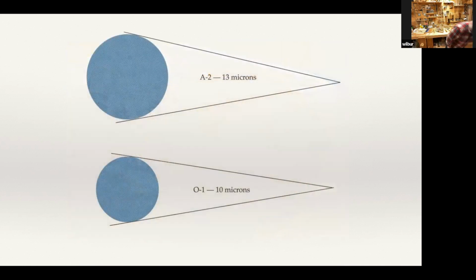Well, as it turns out, these carbides will settle out on a particular size, and this is a combination of how you treat the steel as you make it and the alloys that you put into it. And if you look up material data sheets on A2 and O1 steel, you'll find that you can expect the carbides in A2 steel to be about 13 microns in diameter, and O1 to be about 10 microns in diameter. And in this picture, I scaled the carbides to represent what they would be if they were actually 13 and 10 as we're looking at them.